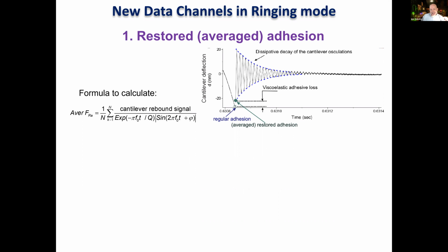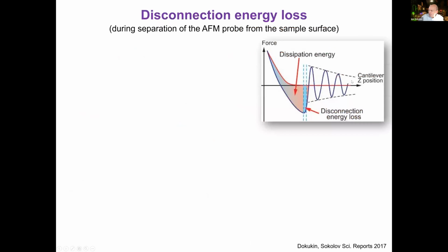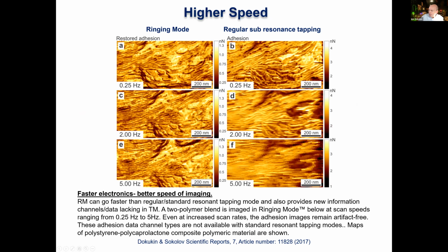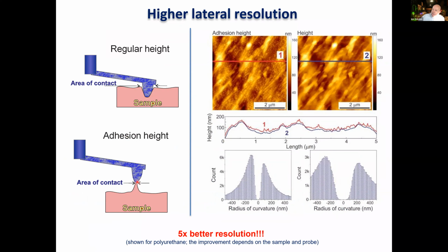some channels, for example height at zero force, probably will not give you a huge difference. But if you go to adhesion height, it is also always a question what is the difference between the area during disconnection versus the area of contact. If you have a big probe, it's probably not super ideal. There is really small roughness there, and it may disconnect at different points all the time.